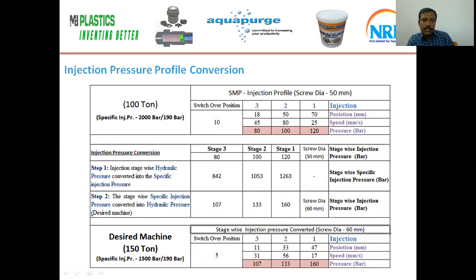Next, injection pressure conversions. We have to obtain the specific injection pressure and hydraulic pressure details from the catalog and the machine controllers. First step, hydraulic pressure is converted to specific pressure. Second step, the specific injection pressure is converted into the hydraulic pressure of the desired machine. So in the 50 dia machine, 80, 100, 120 is the injection pressure. For 60 dia, 160, 133, 107 is the injection pressure, because the 150 ton machine has a maximum specific injection pressure of 1500 bar.